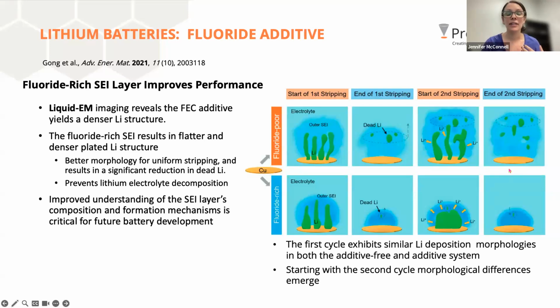That's what they're finding here too: without the fluorine additive, these branch-like structures have pieces that break off and you have dead lithium floating around, whereas you get much better redissolution and much less dead lithium when you have these rock-like formations. With TEM, this was the only way you're able to actually see this occur and the pathway for why this seems to improve battery life.